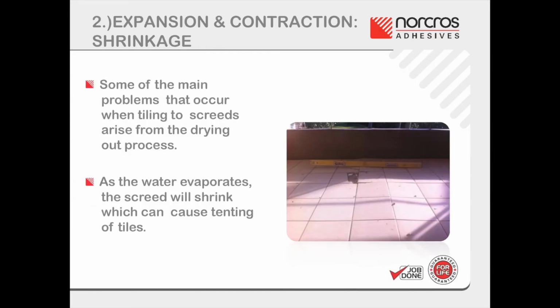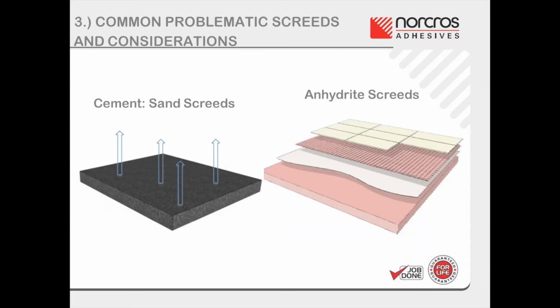The main problems that occur when tiling to cement sand screeds arise from the drying out process. As the water content evaporates from the screed, it shrinks. This can cause problems as tiles may tent if the screed is tiled onto before it is completely dry. Common problematic screeds for tiling onto are cement sand screeds and anhydrite screeds, both for different reasons.